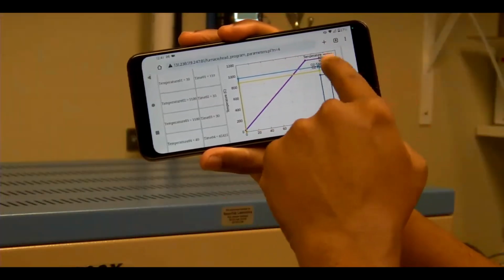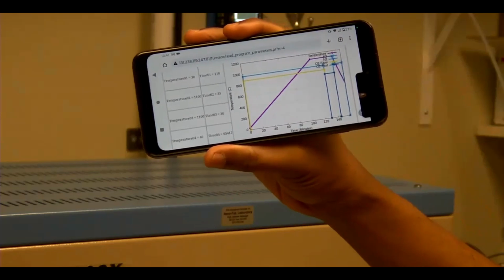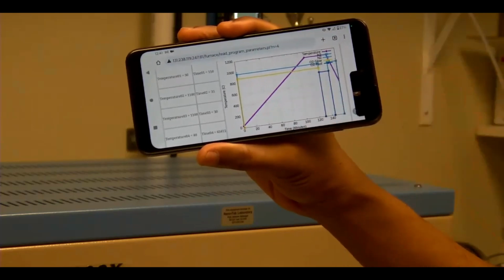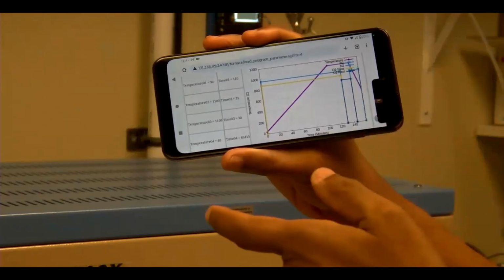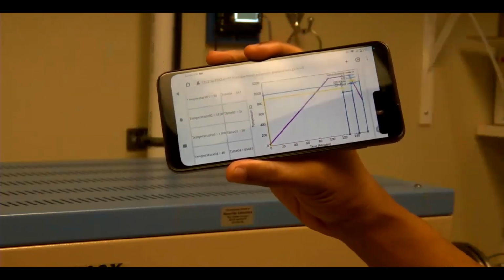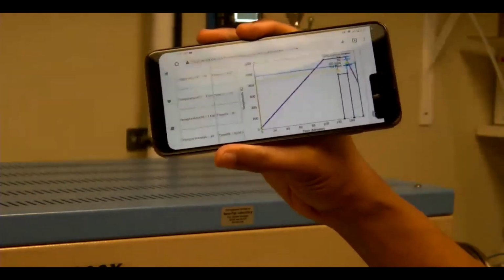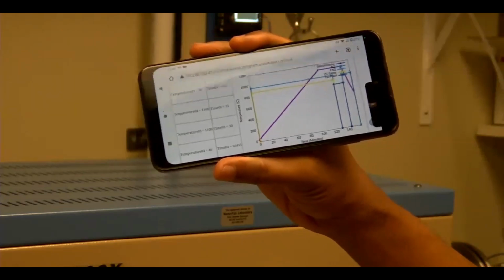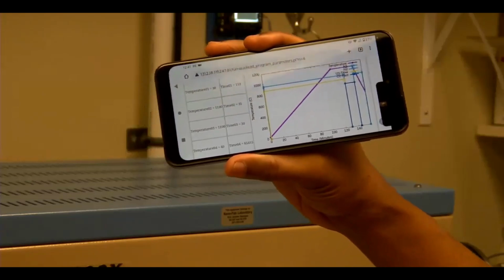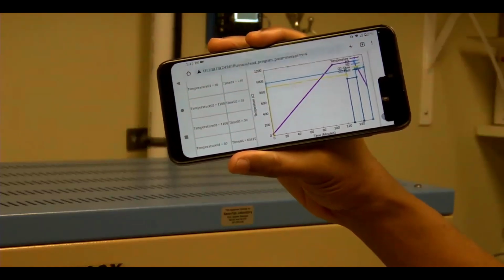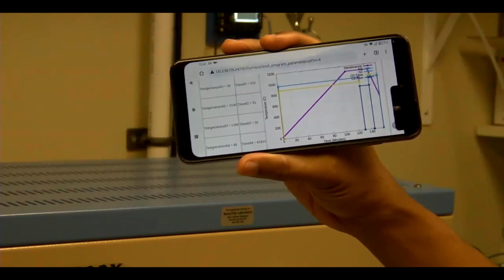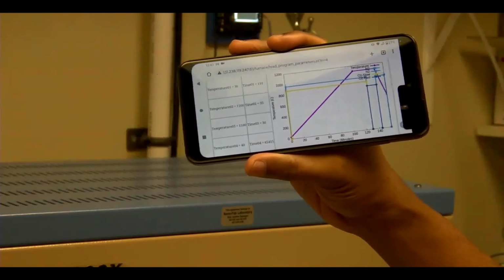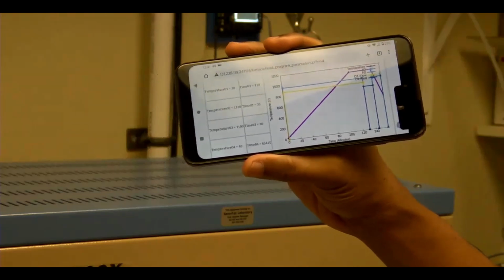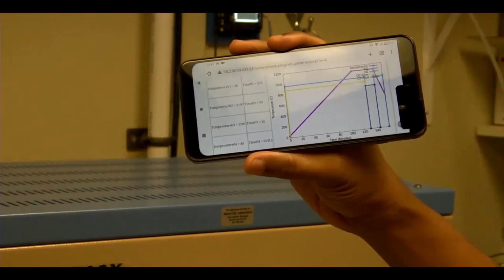So ramp it up to 1100, hold it for 20 minutes, and then keep holding it for another 15 minutes while we switch the gases from nitrogen to 100% oxygen. The purpose of that is, again, to remove the excess boron on the surface by oxidizing the silicon, turning it into borosilicate. So it's SiO2 with boron in it, and that can be etched off. That's one of the drawbacks of this thermal diffusion doping: excess boron on the surface causes some problems, precipitation of boron and all that. You don't get that with implant.